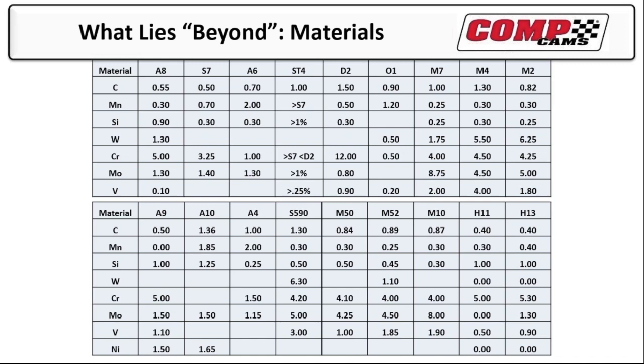One thing you're going to note really quickly is how much more alloy content. You look at A8, it has 5% chromium. That's so much more than what you saw in the other materials. S7, 3% chromium, but only 0.5% carbon. If you look at our grade that we use most, which we had a mill make for us, it's got twice the carbon of S7. So we can use that in a lot more applications than people can use the normal stuff.